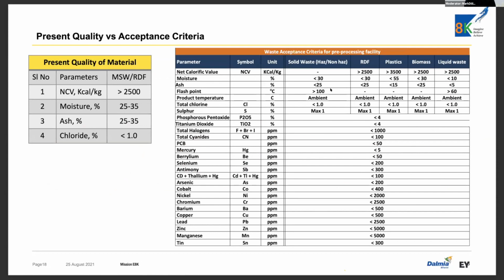As I mentioned, the quality of the RDF is not as per our desire. We require less than 20% moisture, whereas what we get is around 25 to 35% moisture. Similarly, we require ash of less than 15%, whereas what we get is nearly 25 to 30%. All these are creating process problems, as a result of which it's a challenge to increase the quantities of RDF in our kilns.